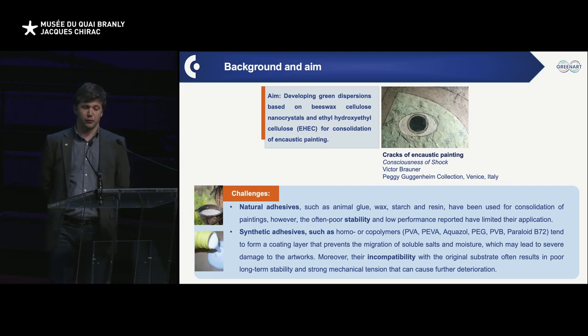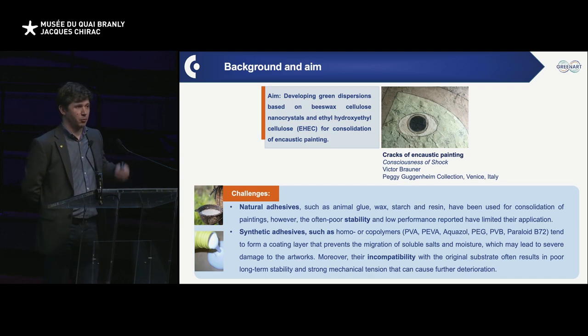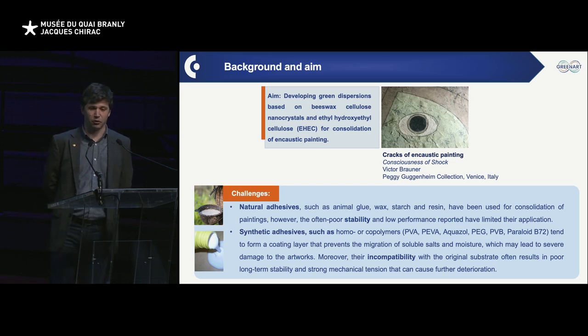So by doing this, we sort of cut on the challenges, and we avoid working only on natural adhesive, such as starch or animal glue that have a tendency to also degrade and are not necessarily the most stable system. We will work with very pure material, essentially, but are still bio-based. And we don't work with synthetic adhesive. That was at the origin of why people at Peggy came to us and asked us, okay, we've been using Aquazol, that was a good material some 20 years ago, but maybe now we need a better solution for it. And well, can you consider doing something about that? So that was the idea and how we started, essentially.